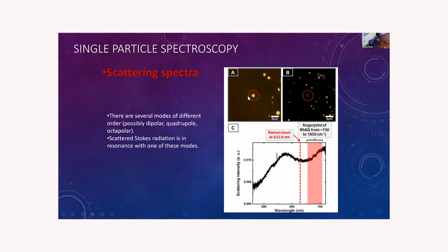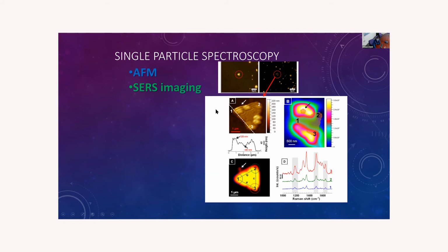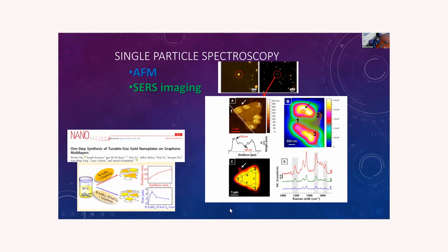When we work with the big nanoparticles, and we perform single nanoparticle, or in this case microparticle, spectroscopy, we took the scattering spectra and also the correlation between the AFM and Raman imaging, or in this case SERS imaging. It was very funny because I was very interested in measuring the optical properties, and I forgot the reason why we got this kind of very big nanoparticles. There were some other people, smarter than us, who published two years after our article, analyzing how it's possible to get this kind of particle in the system of gold particles on CVD graphene.